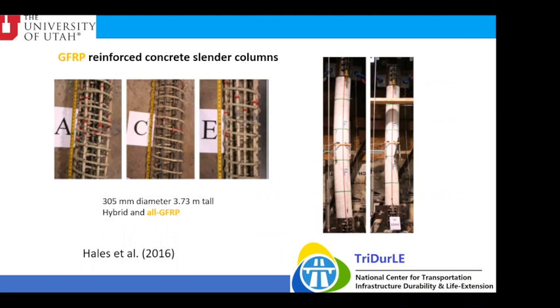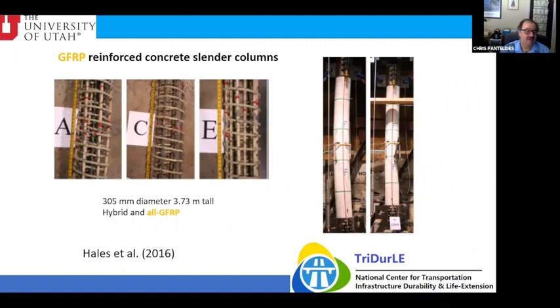Yeah, I'm a little bit curious about the chemistry of the interface, because you're talking about glass, which may actually chemically react with the adjacent cement paste and make the bond stronger. I mean, versus another scenario where you have carbon fibers, which are basically inert, and they're not even hydrophilic, so they don't really bond that well with the cement paste. Right. I'm just guessing. But one thing about that, Xianming, is that carbon is very expensive. They told me in no uncertain terms they wouldn't use carbon for new construction.